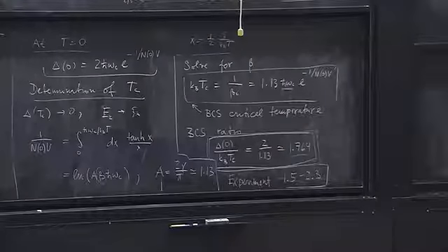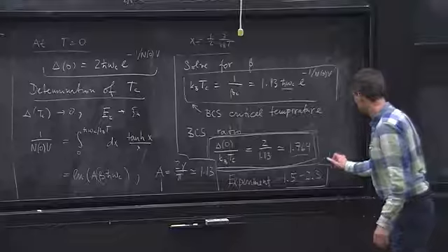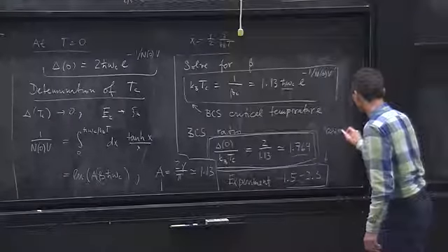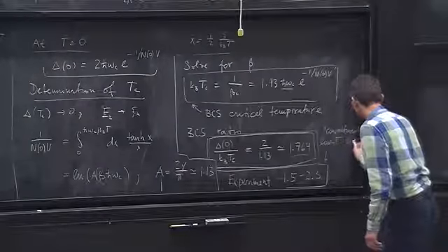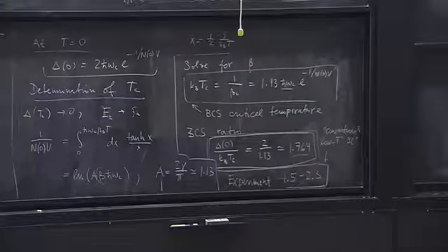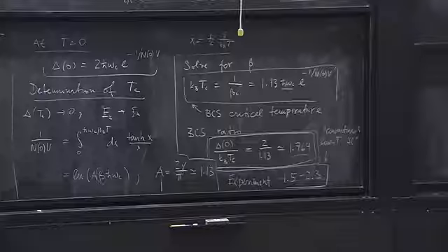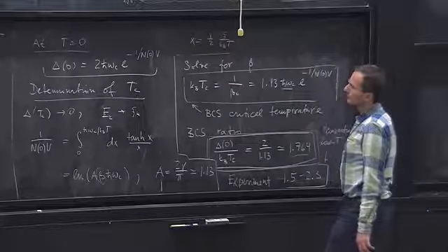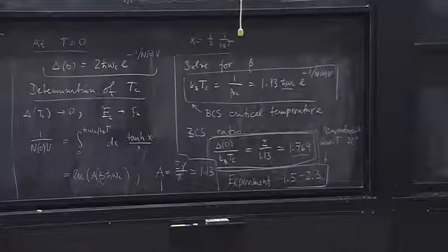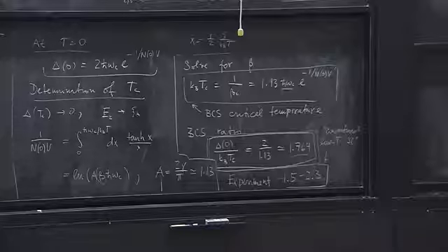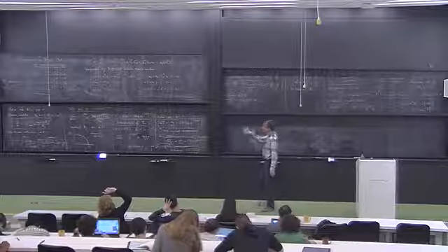Yeah, so this applies to what we may call conventional low T_c superconductors, such as lead, aluminum, niobium, dozens of them that have T_cs on the order of a few Kelvin, 10 Kelvin or so. There are also so-called unconventional superconductors, in which we don't really understand the mechanism behind superconductivity, and high T_c cuprates are the kind of flagship unconventional superconductor. And in those, these values can be as high as 5, which tells you that this theory does not really seem to apply to them very well.